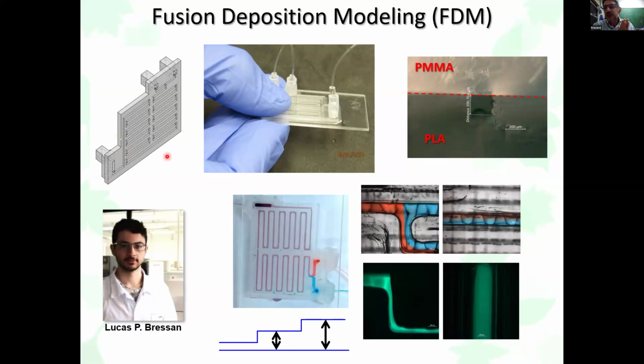And to close the channels, you need to put a substrate and seal the device against this substrate. And we found that some 3D printing materials, for example polylactic acid, you can seal perfectly over a PMMA, polymethyl methacrylate, surface. It's really difficult to remove the first layer of adhesion of PLA against the PMMA. So if you just position a PMMA substrate on the printer and print the device over this, you have the channel sealed in a single step. You don't need an additional step.